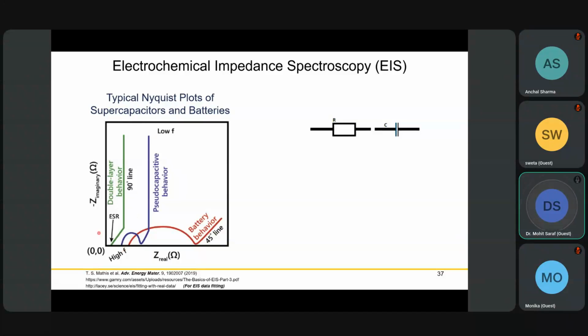This region is the high frequency region, and further away is the low frequency region. So you can distinguish the behavior, whether it is double layer behavior - if it's close to the y-axis, then it's double layer behavior. If you see a semicircle followed by a line, it's considered pseudo-capacitive behavior. In battery materials, the semicircle is very large, followed by a 45-degree line, so we can distinguish materials based on these Nyquist plots.